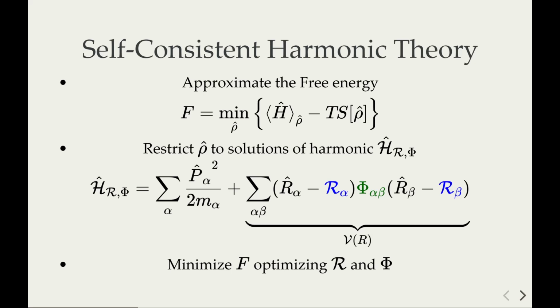So essentially, we map the interactive problem of interacting phonons into phonons that do not interact and satisfy an auxiliary, fake somehow, harmonic system. This auxiliary harmonic system depends on two parameters: the average position of the ions and how much the ion fluctuates, so the effective phonons in this system. Then by minimizing the free energy with respect to these two parameters, the anharmonicity is contained by the fact that the free energy is computed on the fully anharmonic Hamiltonian, and we get an expression for the free energy.